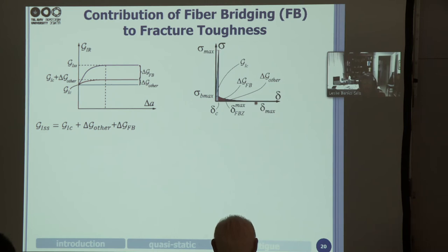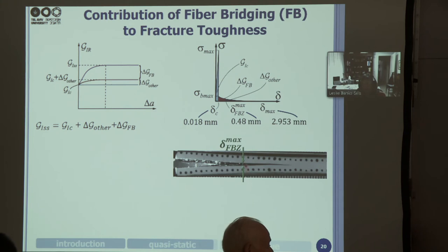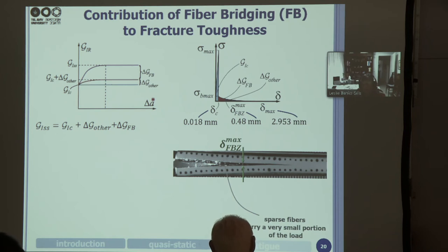We evaluated it by looking at our traction separation law, and we have delta C and delta max, and we measure the maximum opening in the fiber bridging zone. Here we made a big assumption, and I'm sure some people won't be so happy with it: we said our fiber bridging zone is enclosed in our cohesive zone, and when we can't see any light through the fibers, we say that's where the fiber bridging zone ends. Here you can see fibers, but they're sparse, and we claim they don't carry that much load. Those are the sparse fibers, and they carry a small portion of the load, that's our assumption, and the dense fibers carry a large portion of the load.